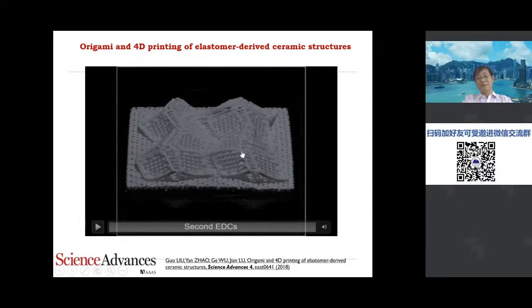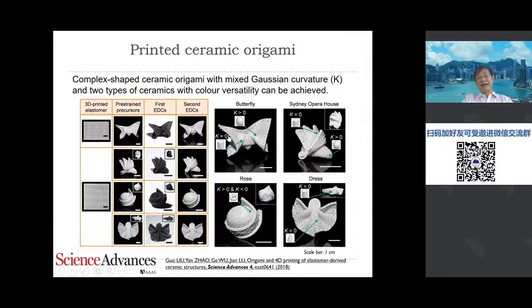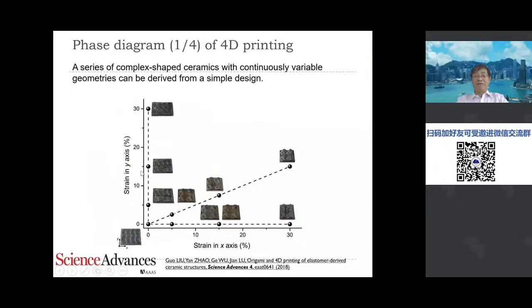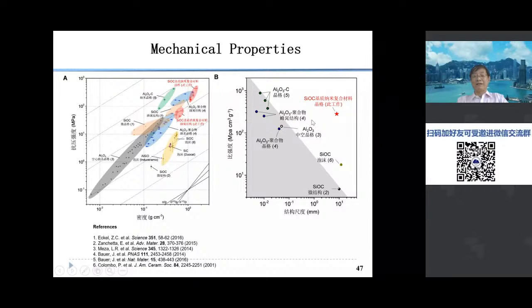As it's a two-dimensional deformation, we can have all kinds of combinations. And as the material is also very deformable, we can also do origami and generate structures that cannot normally be generated by classic 3D printing. Combining different deformation capacities, we can have different shapes of structure. Everything can be programmable and we can obtain plenty of geometries depending on the applied deformation relaxed on the substrate layer. In terms of mechanical property, our material's specific strength is much higher than